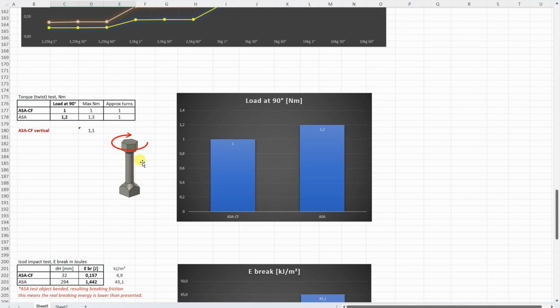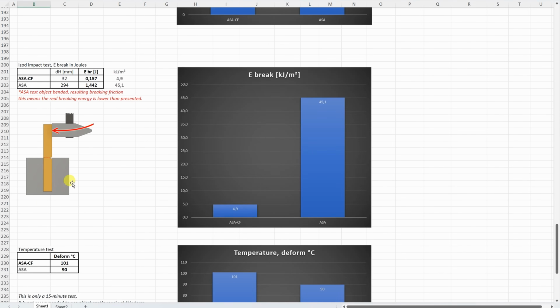On the torque or twist test, this is the load at a 90-degree angle with the horizontally printed test objects. And interesting, the ASA was slightly stronger here. And also I have these vertically printed test objects, but again, I have this only with the CF version. At that time, I didn't do it with the regular ASA.